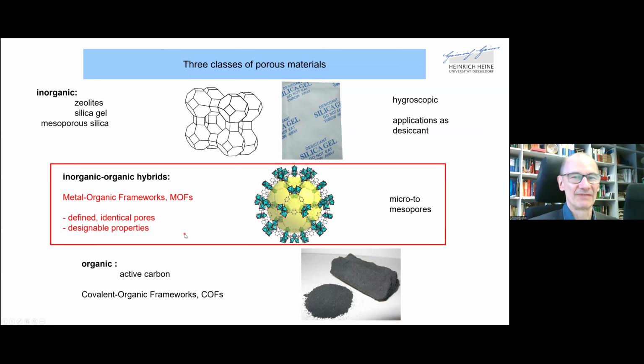And in between, because they are constructed from inorganic parts, namely metals, and organic linkers, are the inorganic-organic hybrids or metal organic frameworks. What sets the metal organic frameworks apart and is special to them is their defined identical pores, because they are crystalline materials. These are also just like zeolites, which are also crystalline, but silica gel and active carbon are not crystalline, but amorphous. So they have a larger variability in their porosity and in their microstructures. And what is also important in MOFs is their designable properties, because the organic linker enables the whole range of organic chemistry to be used as a design function.